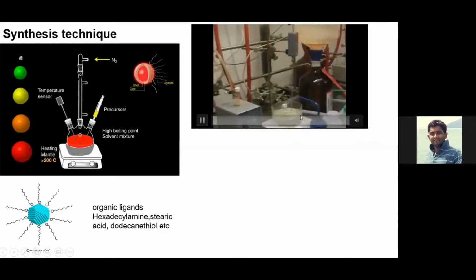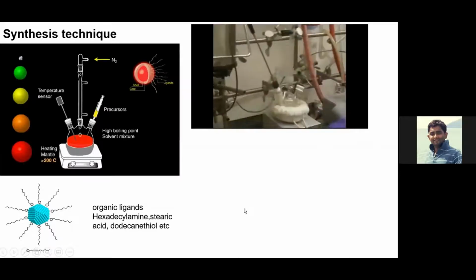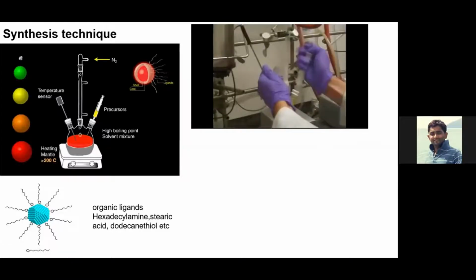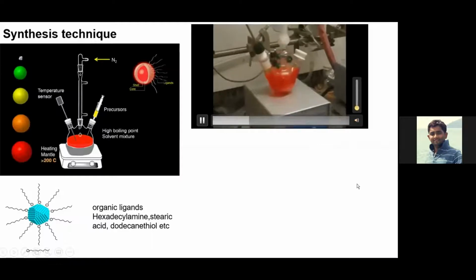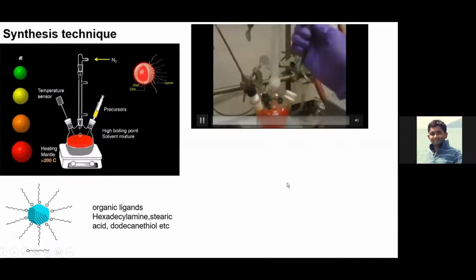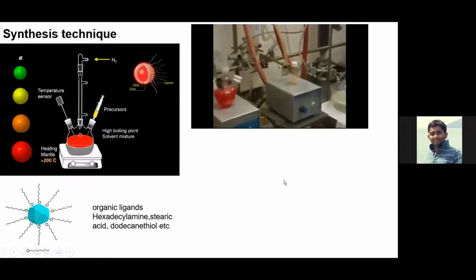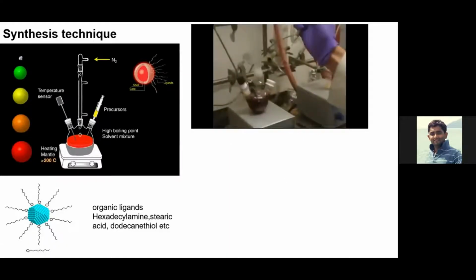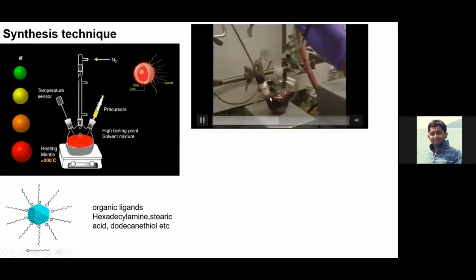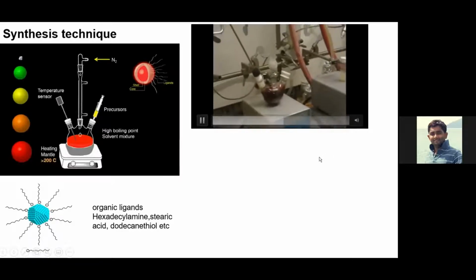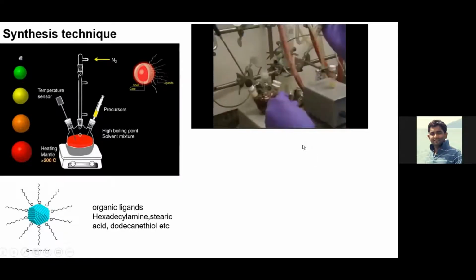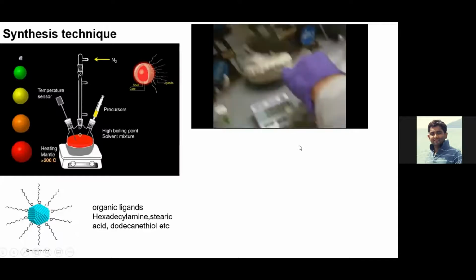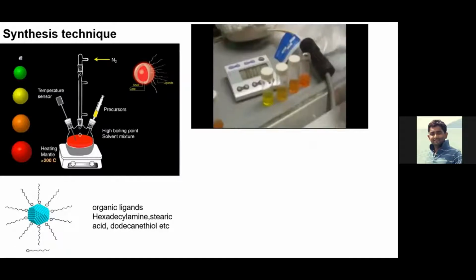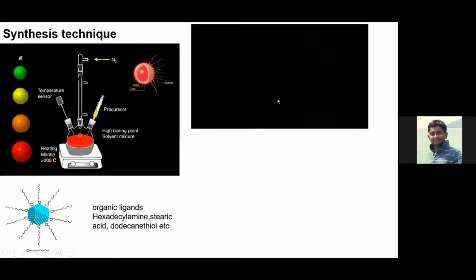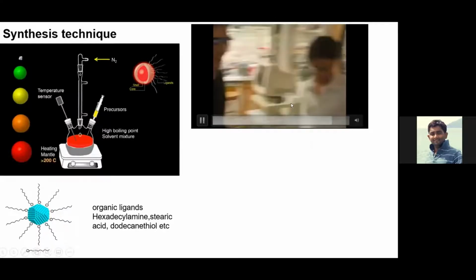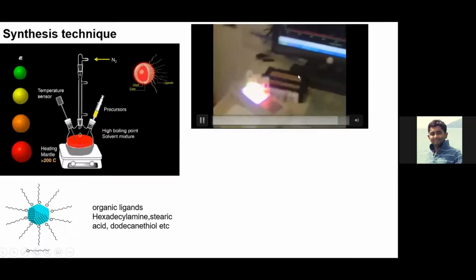So you see, we take a solution in injections, and it's a 3-neck flask. We inject very fast at high temperature. You can see the color is changing, and now it's completely dark, but it's showing the red emission here. And you can see under UV light, it's very bright emission, in very dilute solutions, and you can see the red color emission also.